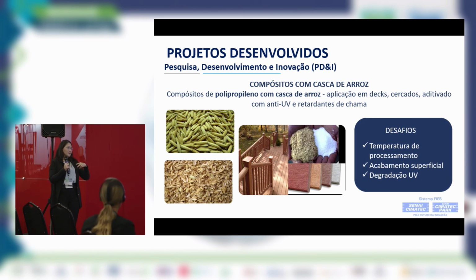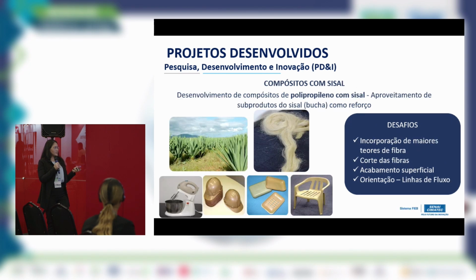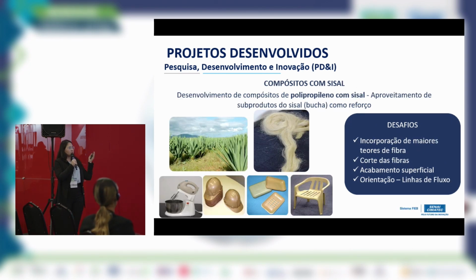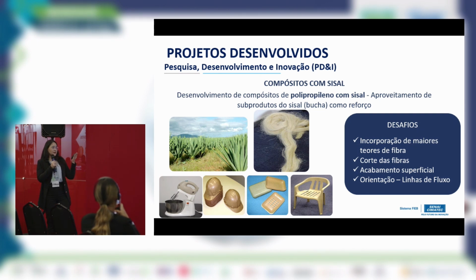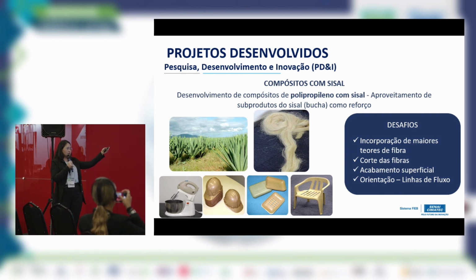Also another issue, superficial finish, because we're adding this fiber that can change the surface. The surface may not be smooth. So depending on the product, we need to be careful. And also the use of compatibility agents, okay? Another example, using PP composites and sisal fiber. So this product used the byproducts of sisal to be a filler in the polymeric matrix. So images about the sisal, the fiber itself that was used, it had to be chopped. We do not develop composites with long fibers. We usually chop the fiber to be able to add it to the polymeric matrix.